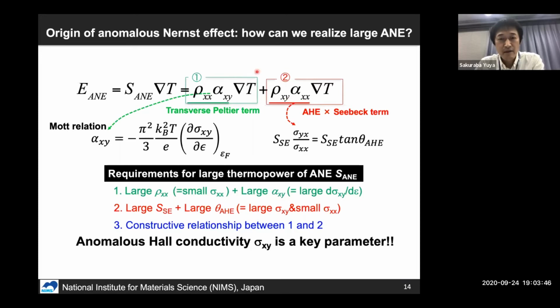So this first term and second term must be large, and the electric fields from the first and second terms constructively work to obtain a high anomalous Nernst effect. And this second term can be converted into the product of the Seebeck coefficient and the anomalous Hall angle. So we can say that a magnetic material having a large Seebeck coefficient and a large anomalous Hall angle is expected to show a large anomalous Nernst effect.